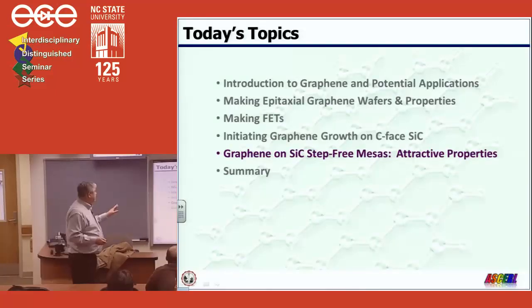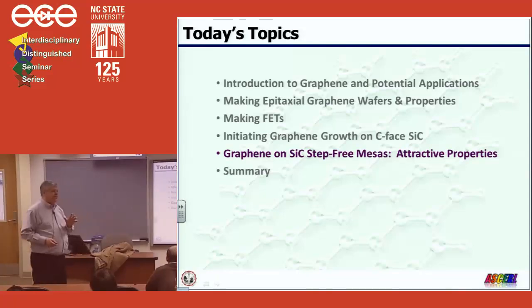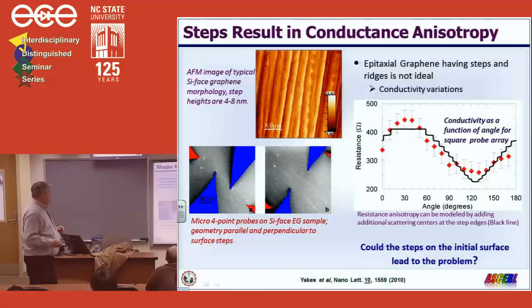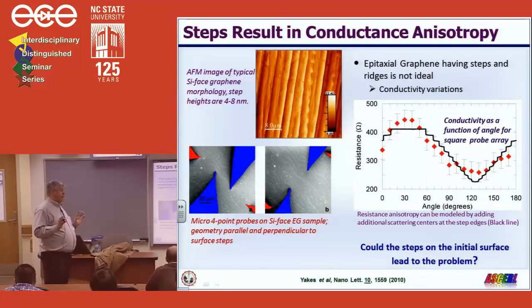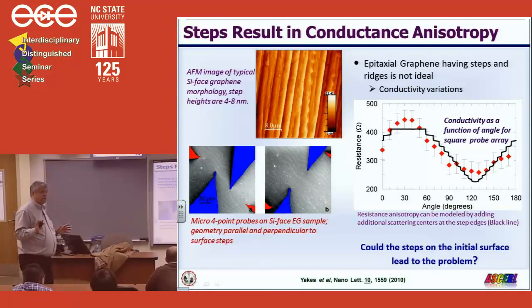And so what we did is we formed step-free mesas. Now, I must apologize, I haven't done it on the carbon face yet. I've done it on the silicon face, only because there was another programmatic reason for working with the material. But we have demonstrated that you grow graphene without screw dislocations, and you get very good quality material. Let me get to that.